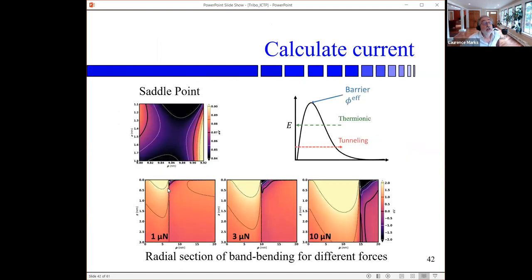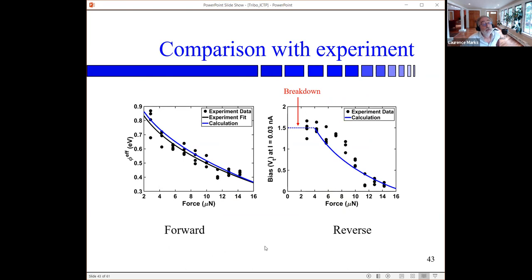You find there is a saddle point: the potential goes up here and down there, and to go from the tip out to the main material you must cross the saddle point, shown schematically here with contours of the real case. Thermionic emission goes over this effective barrier that changes with force, and similarly for tunneling. When you do the calculation, the blue results fit the forward case very nicely. The reverse case is perhaps not quite as good — tunneling is more sensitive to sample details, and almost certainly there is breakdown: the current should continue upward but doesn't.